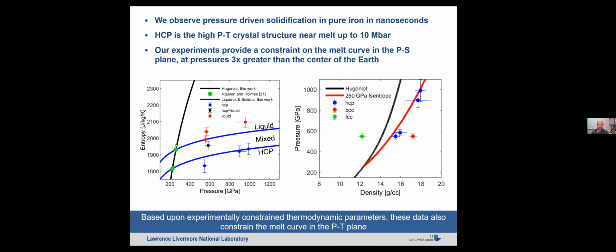So again, now following a horizontal line, say from this pressure point at 260 GPa, you would release and you'd get back on that mixed phase almost immediately, and you wouldn't exit it till around 1000 GPa. So our data is thermodynamically consistent with that picture.